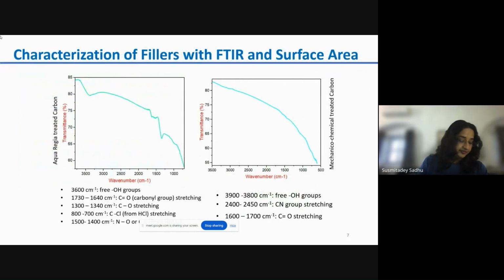The two types of modified carbon black that we have prepared in the lab were characterized again by FTIR and BET surface area. So the FTIR results show that the carbon black modified with aqua regia has developed much more active surface groups on its surface compared to the carbon black which is mechanochemically treated.